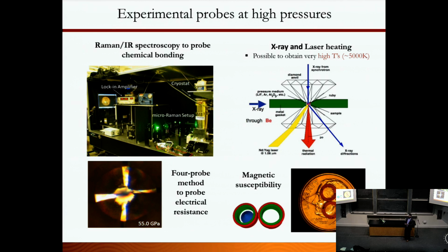And if you want to heat the sample, you can couple with the IR laser and bombard with photons and heat the sample. So you can do high temperature studies too. That's very localized heating. Or you can heat the whole diamond anvil cell. Diamond is a very good heat conductor, so you can put a lot of heat into the sample, but that's kind of limited in temperature region.